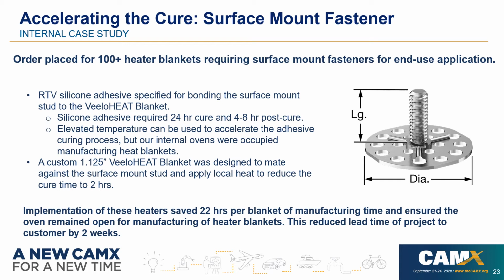With the implementation of these heaters, we were able to save 22 hours per blanket of manufacturing time, and also ensure that our oven remained open for manufacturing, which is really the intended purpose for our ovens of these heated blankets. Ultimately, this led to a reduced lead time of 2 weeks for this project to our customer, and they were very, very pleased with that.